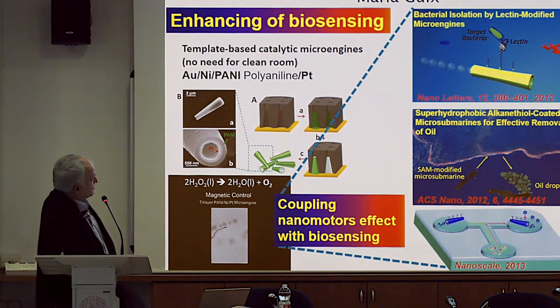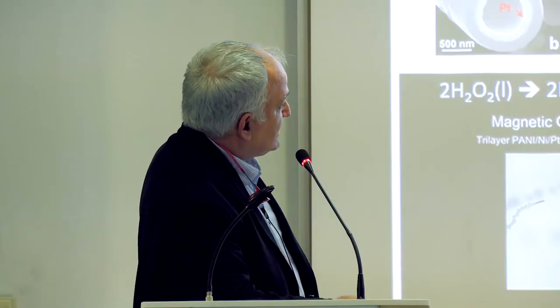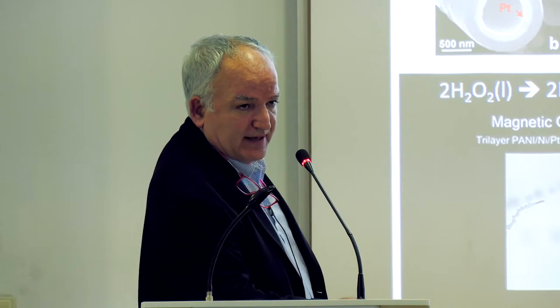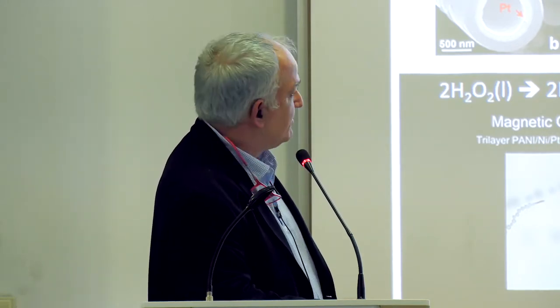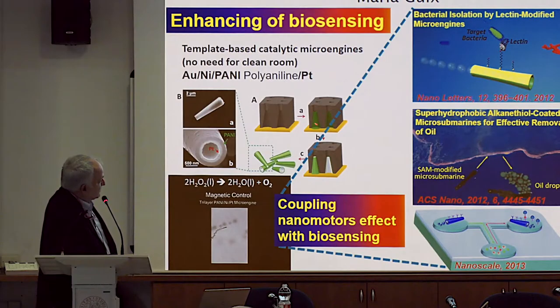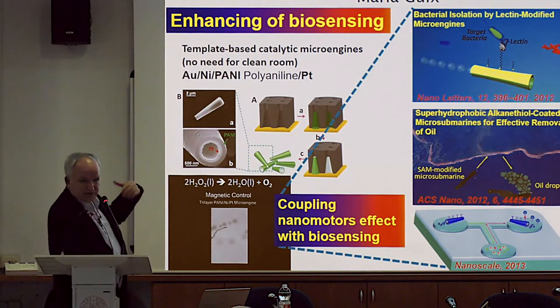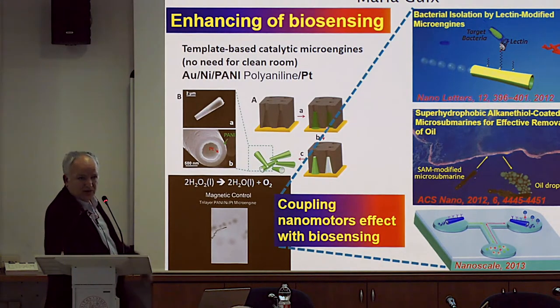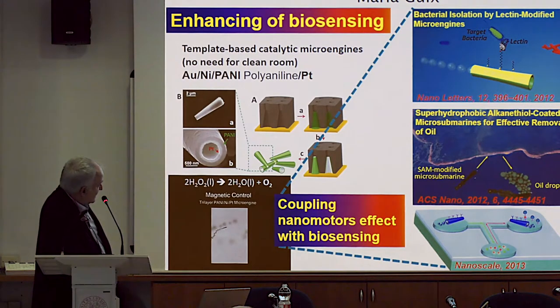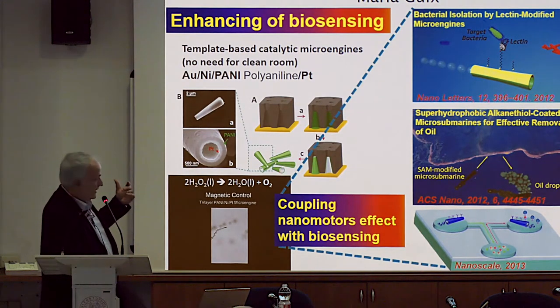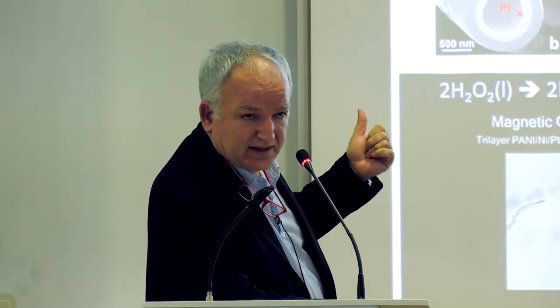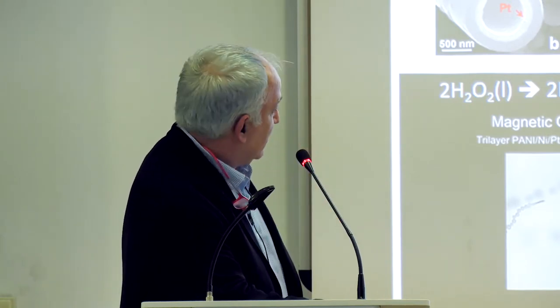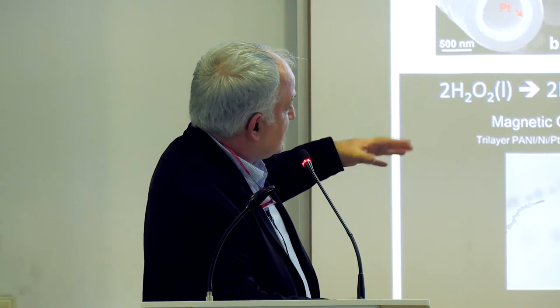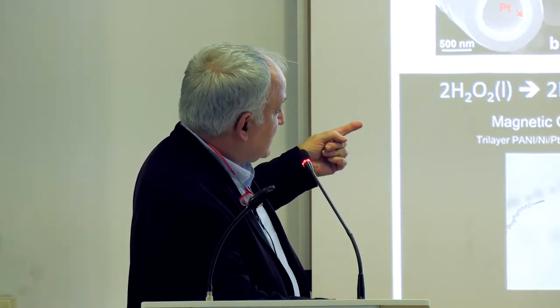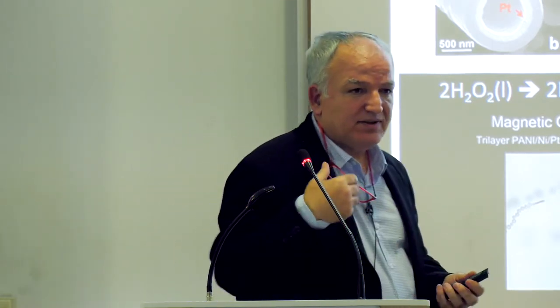So these are tiny devices that we produce by electroplating. So we electroplate this using some molds. So these are some porous membranes made of polymeric membranes, where we electroplate different kinds of materials. For example, we can put here also platinum, we can put magnetic layers, we can put also other kinds of metals. And after dissolving the membrane, we get these nice cones that have very nice properties. So they have inside platinum, they have inside a magnetic layer, they have inside also some receptors we can put. When you put these cones in a medium of hydrogen peroxide, oxygen is delivered, and the bubbles of oxygen are serving as a propulsion force.